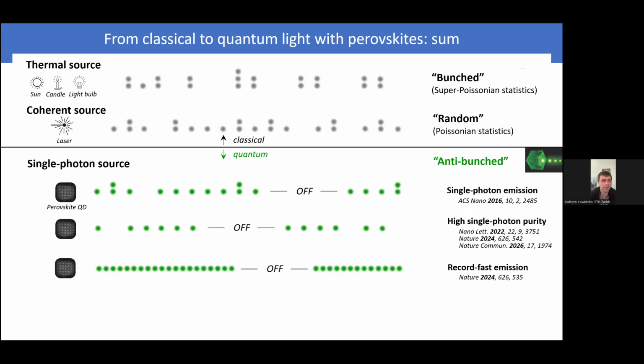So this compromises a lot in terms of intrinsic semiconductor property. We do work on that, so we will soon publish one paper where we show how to improve that, how to fight against that self-doping while preserving these materials from oxidation. And we will show in future how to do compensation doping, which we're working on. So long story short, Dmitro, there is an alternative and only one, which is tin. All other halides have problems or end up with highly self-localized excitons, which are way slower as emitters.